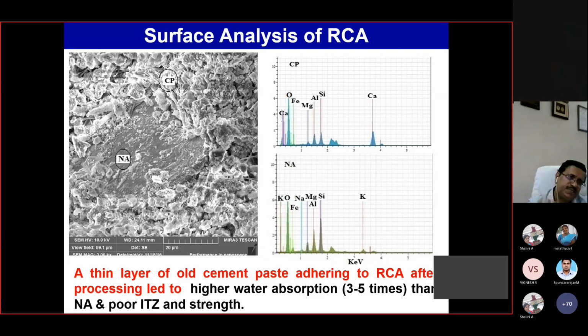If we can improve this adhered mortar zone, either by removing it by grinding, or by a carbonation route, we can achieve a good aggregate from this recycled concrete. That was our major concern to look into. This is why the adhered mortar is loose. Similarly, the fine aggregates all have some elongated parts as recycled fine aggregate. Other than those materials, there is silica, with rivers having high silica content, and this has calcium carbonate content. But here you have to get some calcium silicate hydrates and other cementitious binding properties.